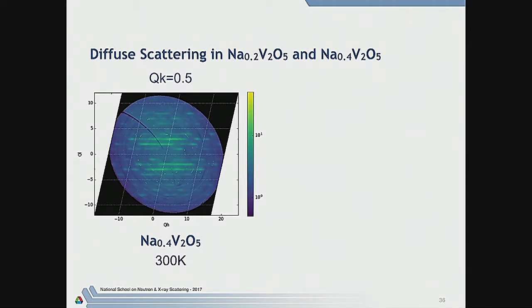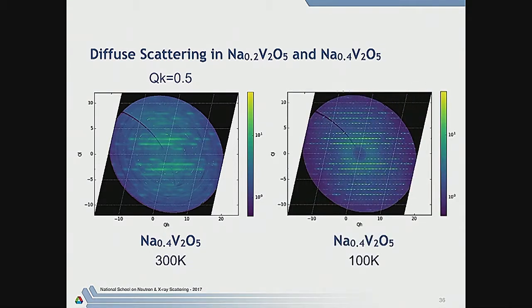So we did the diffuse scattering measurements, and this is what we saw: these rods of scattering. This is the k equals a half plane, so there are no Bragg peaks. This is h, l, and k equals a half. So all the Bragg peaks are in the k equals integer planes. We just have these diffuse rods, and that represents disorder coming out of the sodium sublattice. Now, this is at room temperature. When we cool down to 100 Kelvin, a lot of the rods actually started developing Bragg peaks. In other words, we've gone through a transition where we develop long-range order in the sodium sublattice.